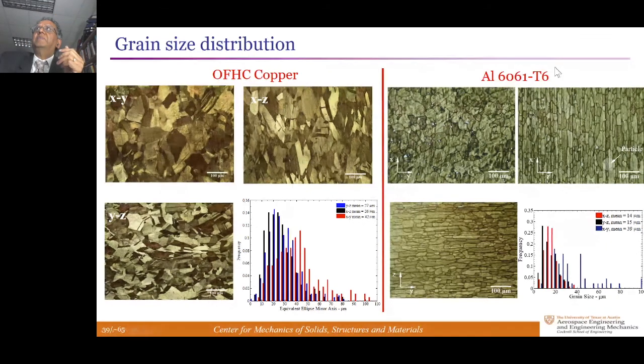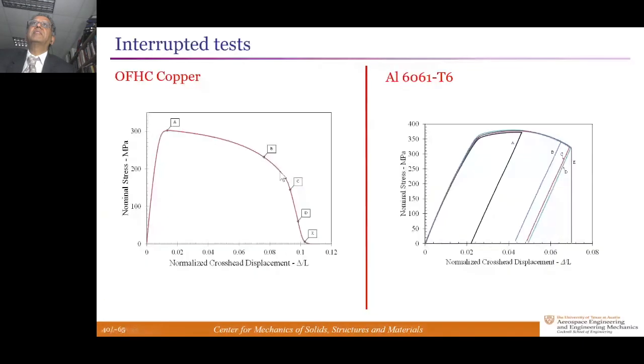On the right-hand side is a 6000 series aluminum alloy. This is age-hardened to T6, and so it has precipitates that are on the scale of the lattice level, but they also have second phase particles, some of which are identified here, that are bright white in this etched picture. Once again, you can see the grain size distribution. They're on the order of tens of microns. The volume fraction of the second phase particles is less than about 1%. These are hard particles, and they do play a role in how the material on the right deforms and fails as opposed to the one on the left.